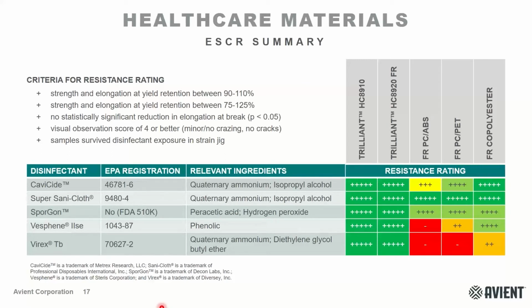And all of this is basically what I just talked you through, putting that into a scale. So number one, did the samples survive the disinfectant exposure in the strain jig, or did they fail entirely? So you get a plus for surviving the strain jig. And then there's the visual observation score. This is a 5-point scale that our technicians provide, where a 4 or a 5 represent minor or no crazing, as well as definitely no cracking. So that's another criteria. And then the final 3 are dependent on the tensile retention data.